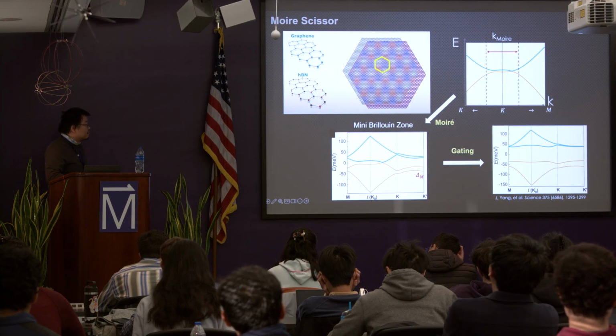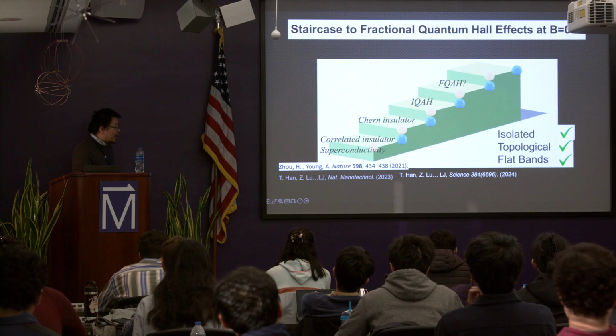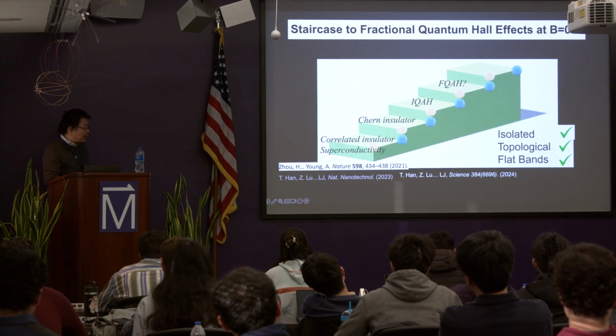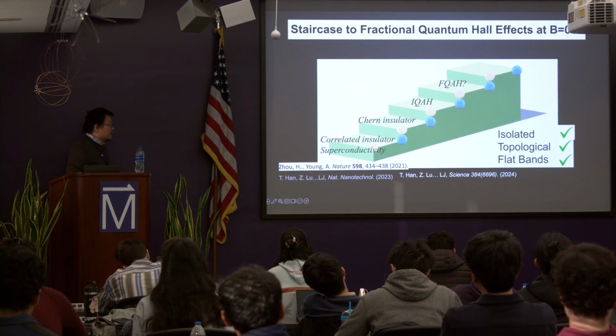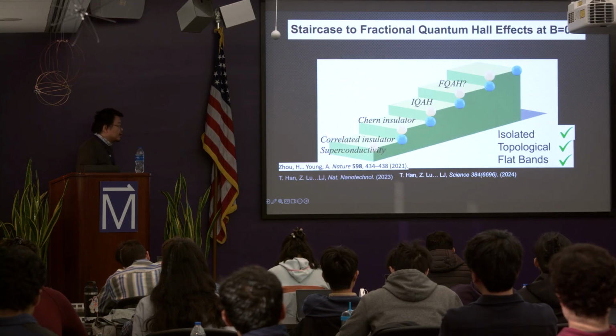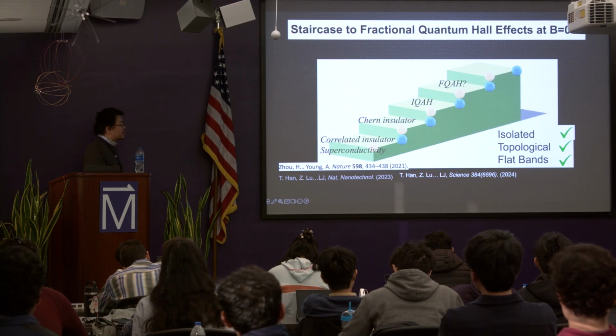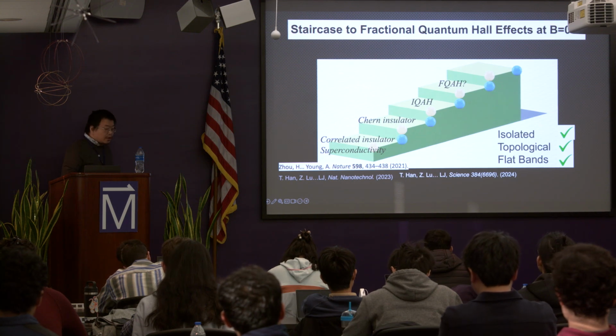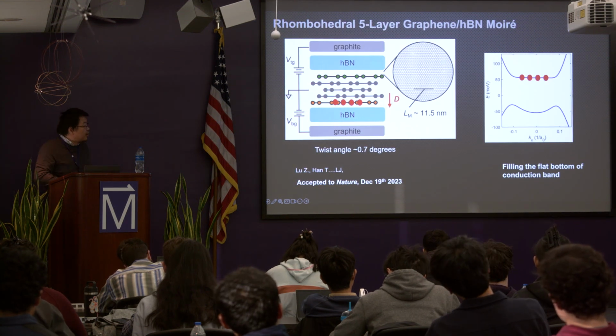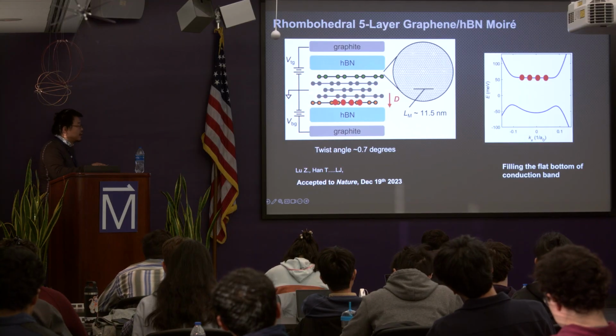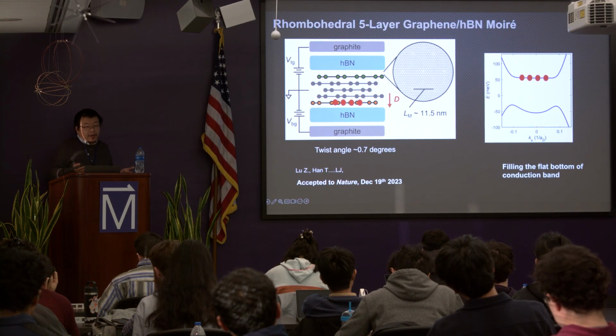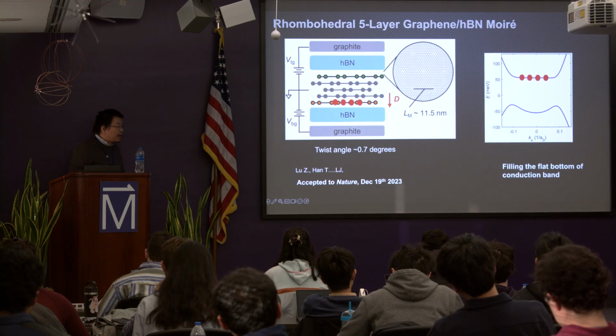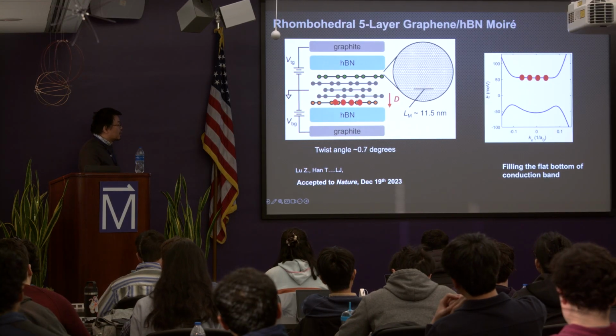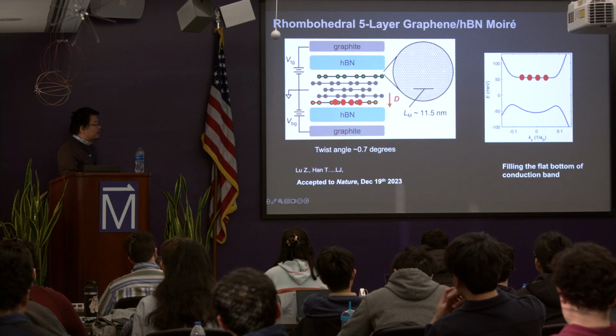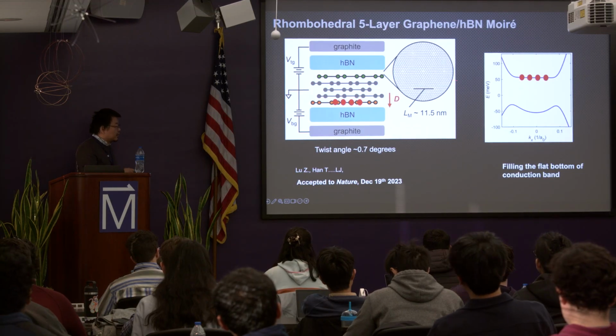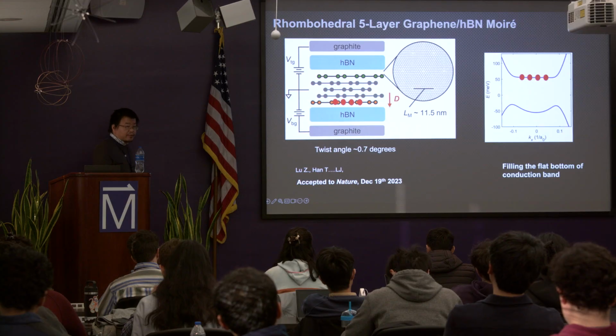With all these tools, you sort of have isolated topological flat bands in the system. Although it's all pretty hand-waving, let's see if in this way we can actually have fractional quantum anomalous Hall effects. So the experimental setting is you have a 5-layer rhombohedral graphene in the middle, because the band is relatively flat compared to the thinner layers, and then you have one side that is aligned with hBN, forming the moire superlattice with a wavelength of 11.5 nanometers.